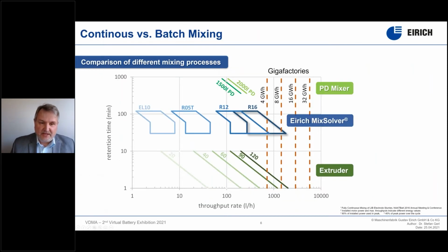If you compare different mixing systems, and I have made this here with a special chart where I put the retention time over the throughput rate in the log-log graph, we have on the one hand the classical PD mixer, with preparation times of 6 to even 12 hours and more. And we see that with a 1,500 liter PD mixer, or even with a 2,000 liter PD mixer, we have a throughput rate which is in the range of about 100, maybe 200 liters, and will go down, of course, if you increase the time.